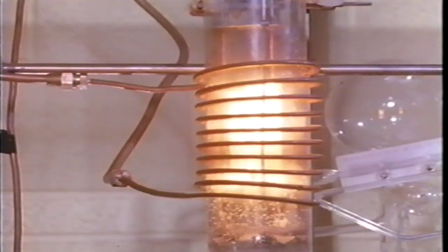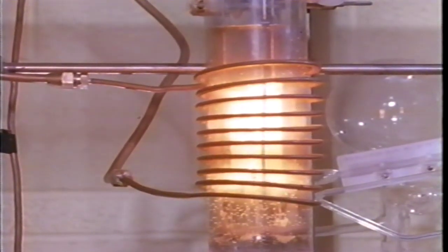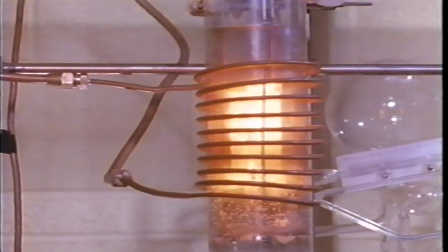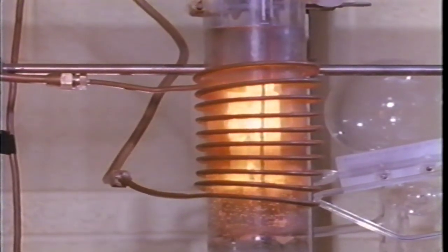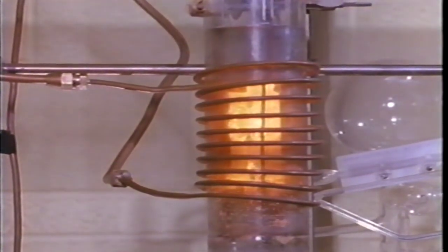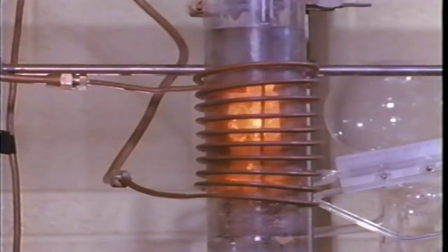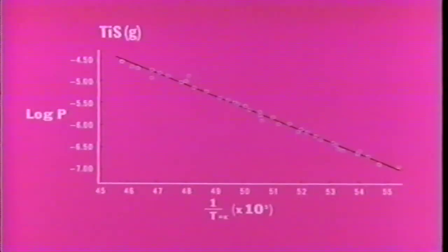Additional experiments at different temperatures enable us to calculate how the pressures of the individual gases vary as temperature changes. This variation is intimately related to the bond strength of gaseous TiS through Le Chatelier's principle. Here are the data for gaseous TiS. The logarithm of the pressure of TiS is plotted against the reciprocal of the absolute temperature. Here is the area of high pressure, and here, low pressure. Here, high temperature, here, low temperature.